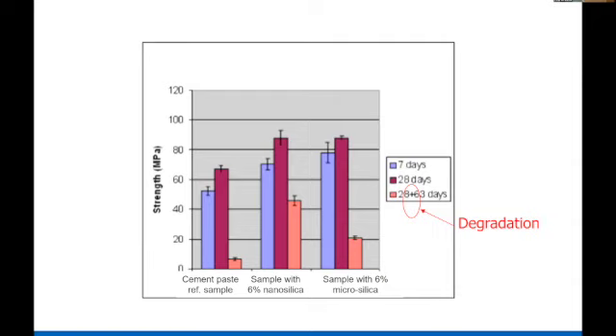So what I've shown here is the compressive strength, 7 days, 28 days of normal curing, and then 63 days of accelerated calcium leaching. So the first one is the control specimen, and you can see a substantial reduction of compressive strength when calcium is leached out. So when you add silica fume or microsilica, which is very commonly used, the reduction in strength is less. But with the same amount of nanosilica, the reduction in strength is even less with nanosilica as opposed to microsilica.